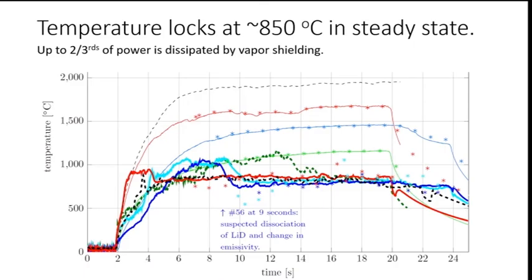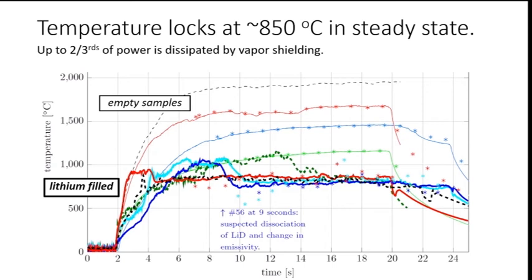Okay. Now, the temperature is maybe the most trivial thing, but it's also, I find, the most interesting and most insightful thing. So what we see here is a striking difference if we view the temperature over time between samples that have been put in as a reference, so a 3D printed sample without any liquid metal inside, and on the other hand, samples filled with lithium.